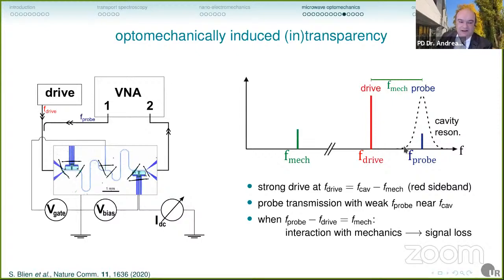Now you all know, if you apply two AC signals to one object, then you get sum and difference frequencies. And that means if the distance between the drive and the probe is exactly the mechanical resonance frequency, then we get a beat at the mechanical resonance frequency, and that beat drives our mechanics. And that means energy gets lost, so we get a decrease in transmission of the probe tone. So we should see a small dip when this precise resonance condition is achieved.